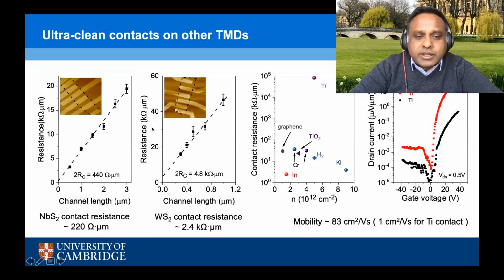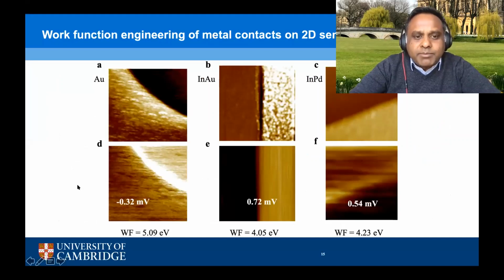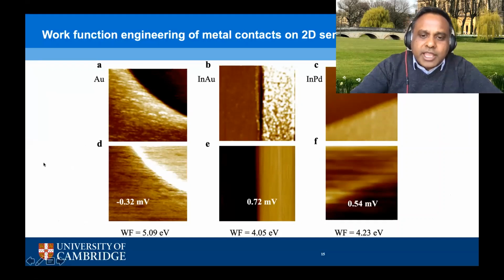And so this works on any 2D semiconductor. Niobium disulfide is a metallic 2D material, so one can achieve very low contact resistance values of the order of 200 ohm micron. On tungsten disulfide, we get low contact resistance as well, and that translates again into very good device characteristics with much higher current than if you had a defective titanium contact on tungsten disulfide. And so we're quite happy with the indium deposition. Now I think there are groups in Korea, in the US, and in A*STAR who are actually depositing indium capped with gold or some other metal as a very high quality contact.